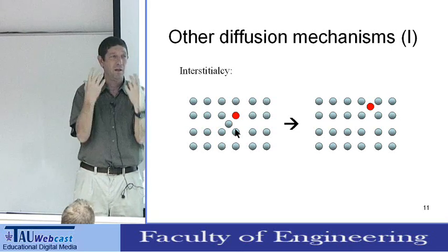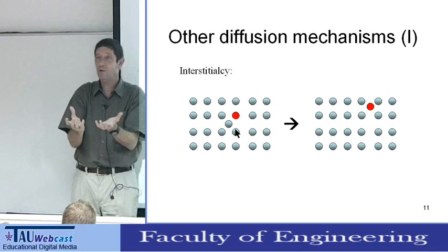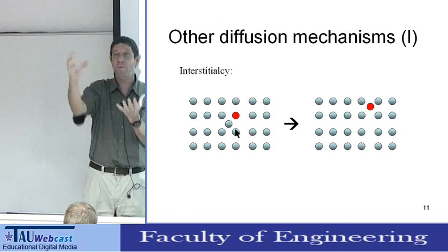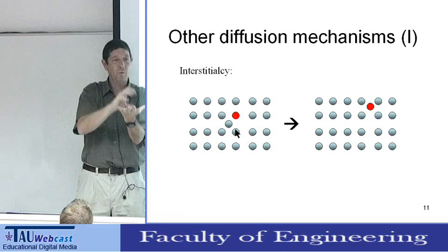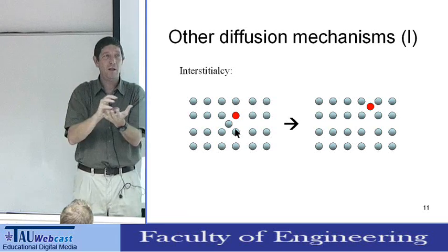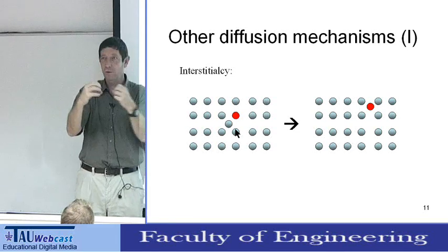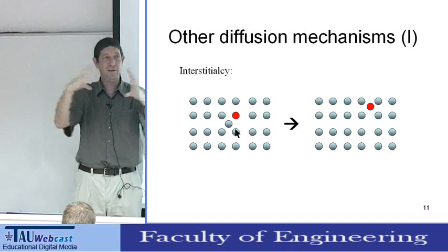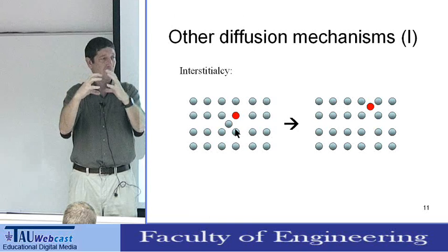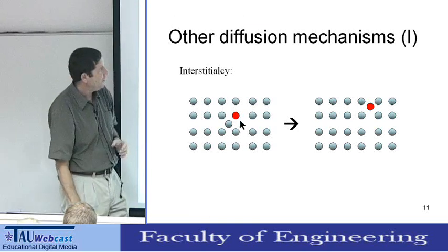And you have to take all this into consideration, because what determines the jump of the atom is how much energy you need to move the atom from one place to another place. This energy can be chemical because of the bonding, and can also be mechanical because the lattice itself is holding the structure.